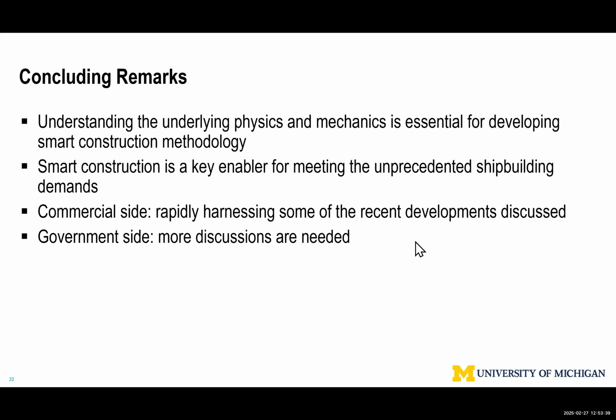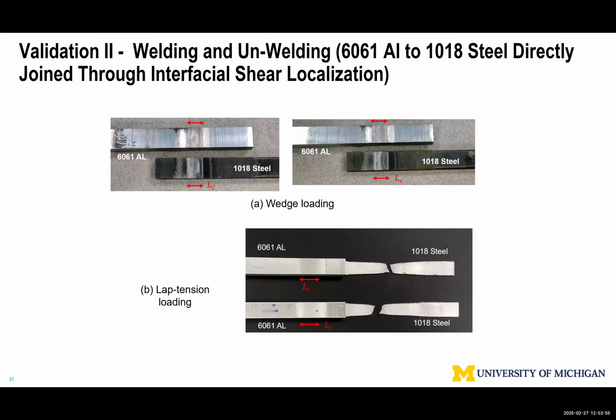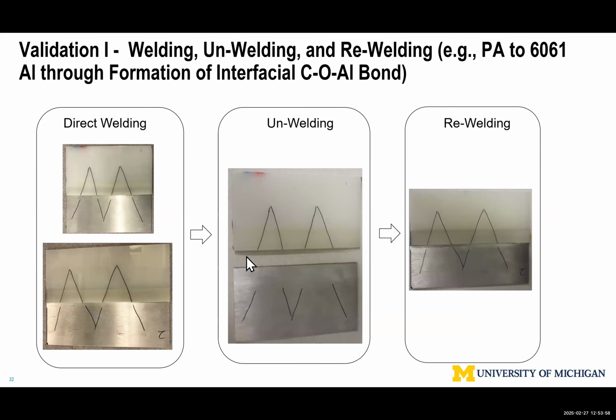So you were talking about crack propagation at the interface between the two materials. What is the behavior of that crack propagation when it's coming into the interface perpendicular? Very good question. That's the trick, right? By definition, if you want to reuse material, reuse a piece part, you want to have the crack propagation along the interface without damaging nearby material. If you want that joint to perform best under all kinds of loading scenarios, you want that crack to go into the material, stay away from the interface.